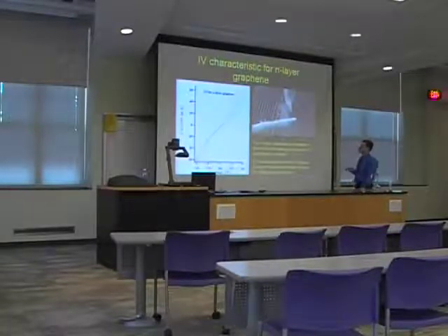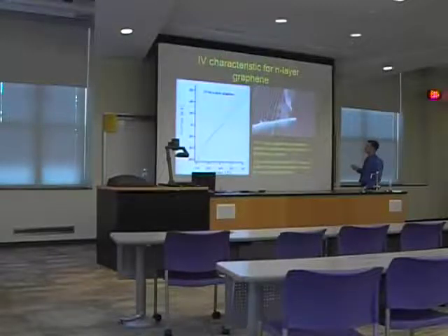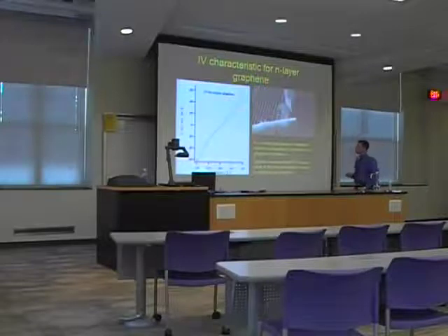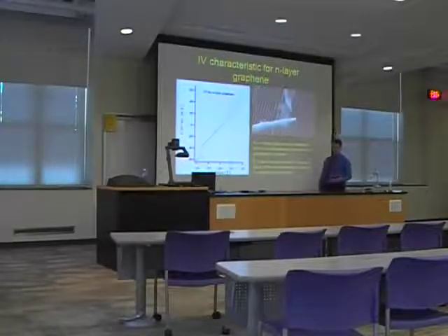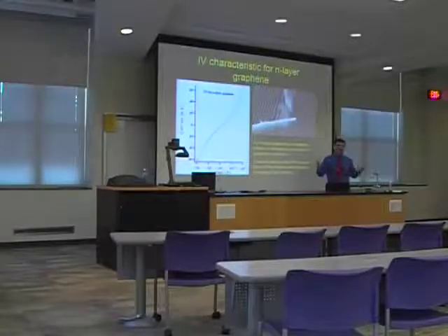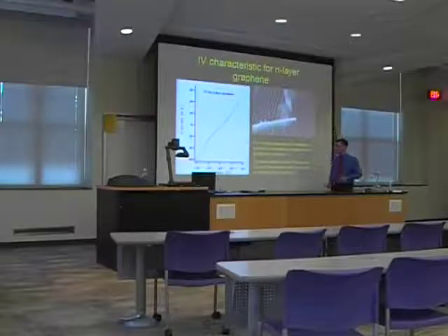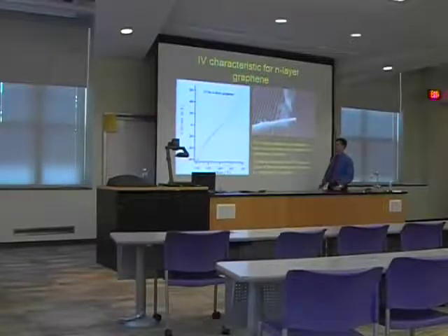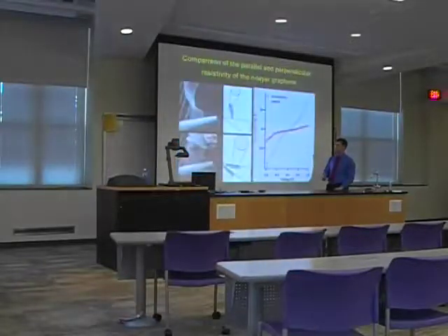For a group of layers, this is already like 4 or 5 layers of graphene between the electrodes. And we put a little gallium on the tips to improve contacts. Conductivity is sufficiently higher. The reason for this is obvious, more or less, because now we have propagation through bulk, not just through one atomic layer. And in this case, we obviously expect an increase in conductivity.